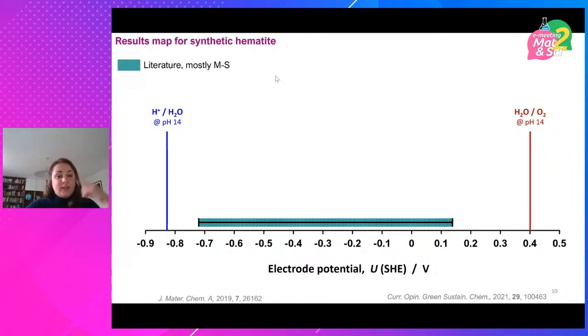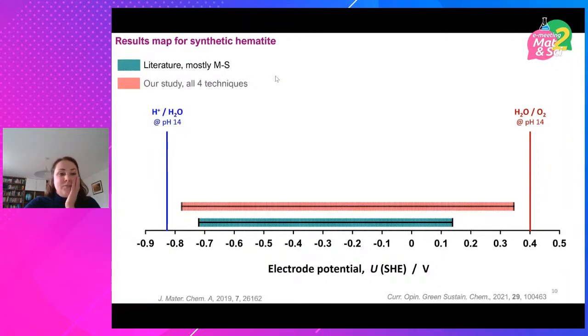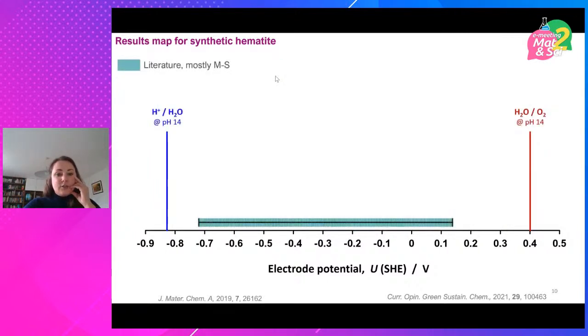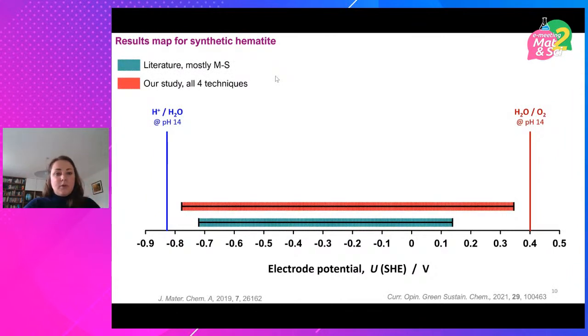So then what I did is I had 3 identical hematite electrodes and I did the same measurements for all of them, just to check that it wasn't one electrode that was faulty and the rest were fine, just to get an idea of reproducibility. And what I found is that with all of our 4 techniques, if you combine all the data, this was the range of flat band potential values. So the difficulty, and the reason this work took something like 6 years to complete, is because we really struggled to explain why every technique was giving values that were so extreme. And most importantly, which one was most reliable.